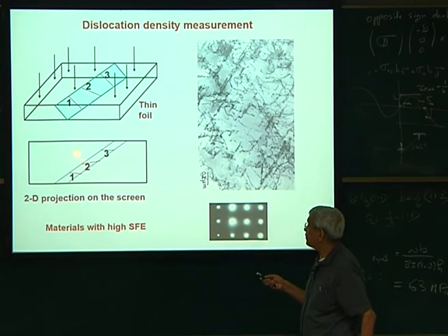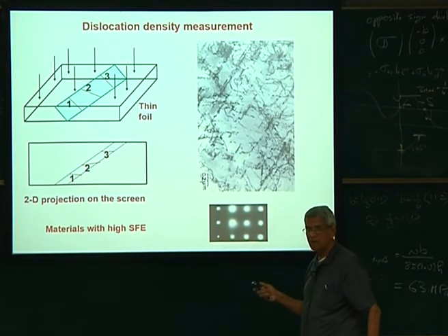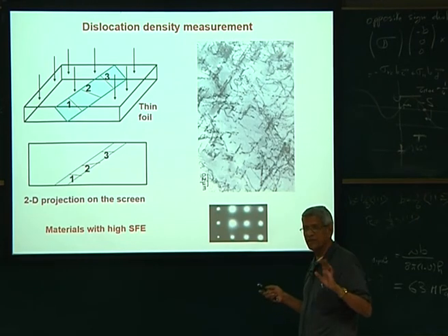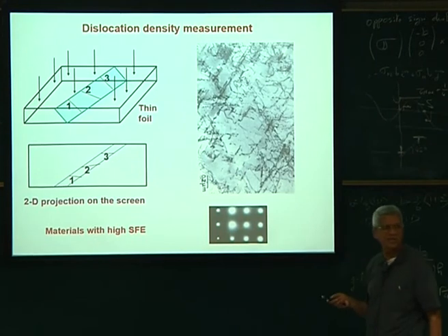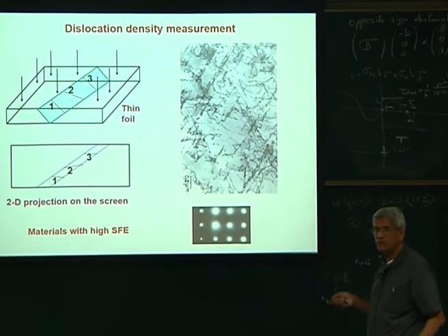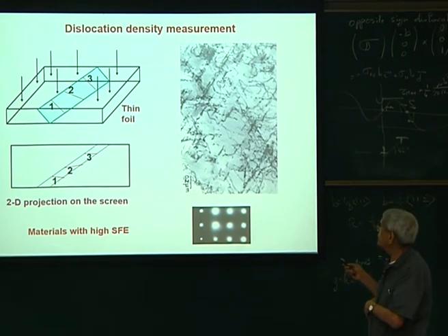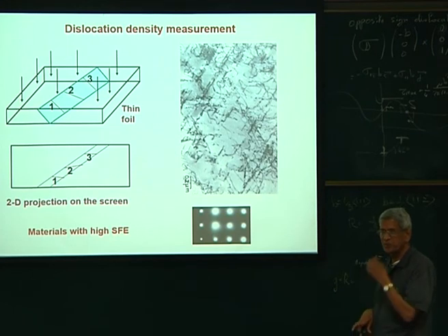For which first what we have to do is measure the distances of this dislocation and add all of them together, projected dislocations, and these are lying within this particular one. Still some error is going to be there associated with it. Okay. I am just showing a picture which I had shown where dislocations are imaged, a lot of dislocations are there. There are many image softwares with which the total dislocation density could be determined.